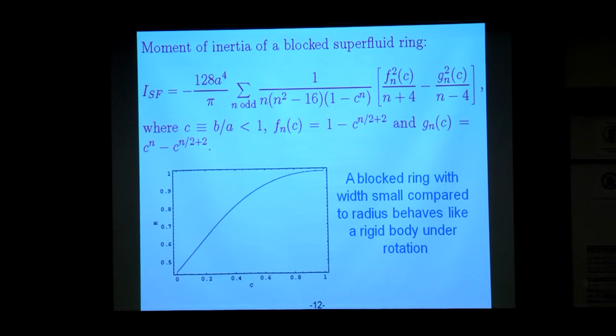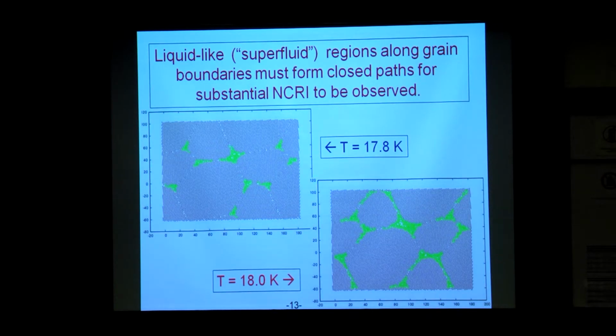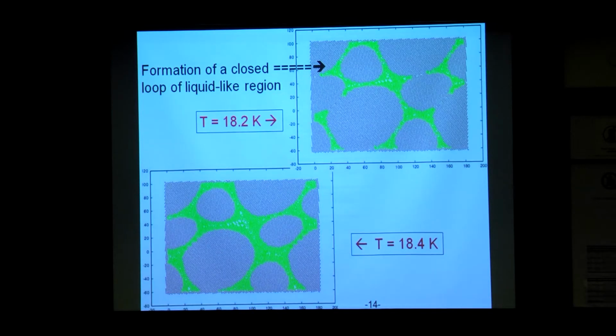So then we looked at these pictures that we got from our work on the vortex problem, and there the parameter that we changed was the temperature. This is at low temperatures, where the melting near the grain boundaries occurs in very, very small puddles. As we increase the temperature, these puddles become bigger. They tend to merge with each other, join with each other to form bigger structures. And eventually, as one goes to higher temperature, which of course depends on many of the parameters that we put in the vortex problem, one begins to have these closed loops, and the loop size, at least in our finite system size, is comparable with the whole system size.